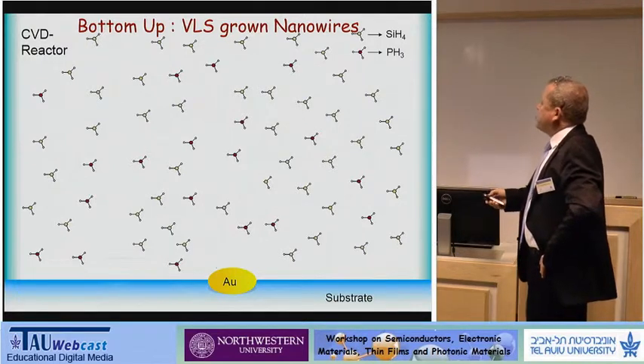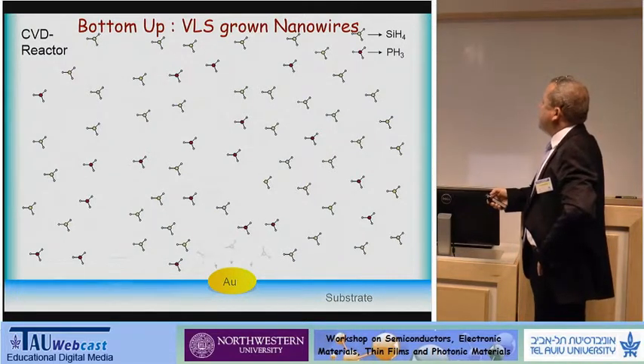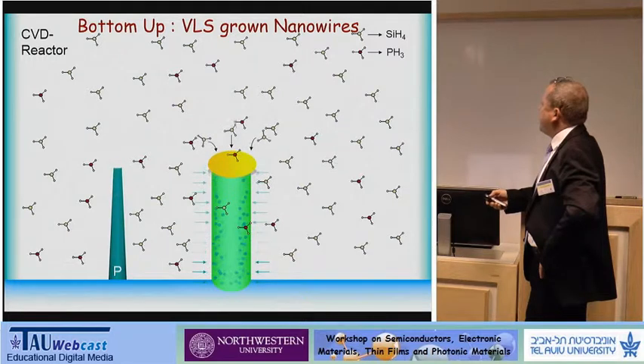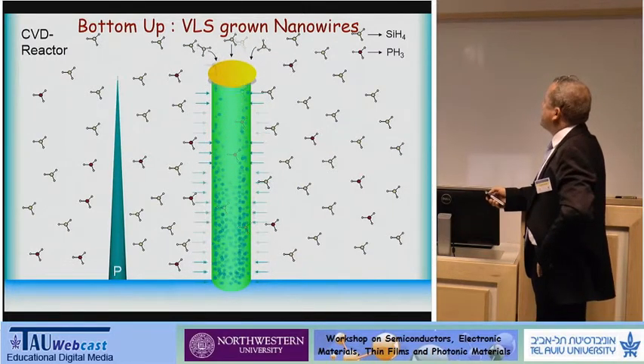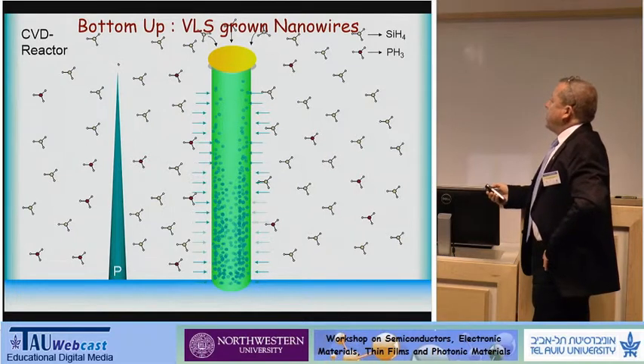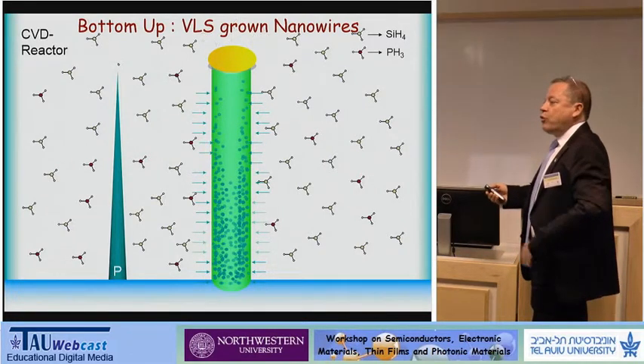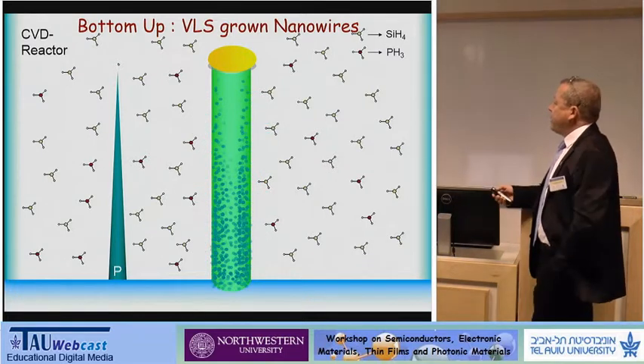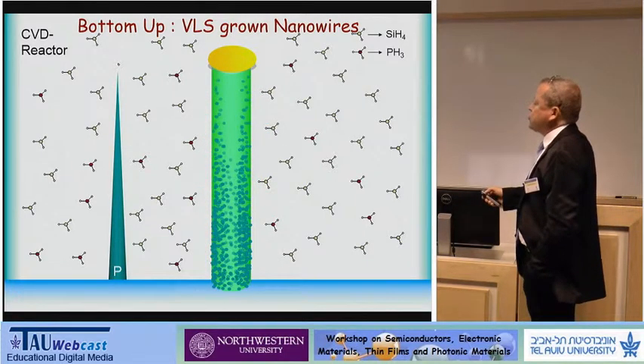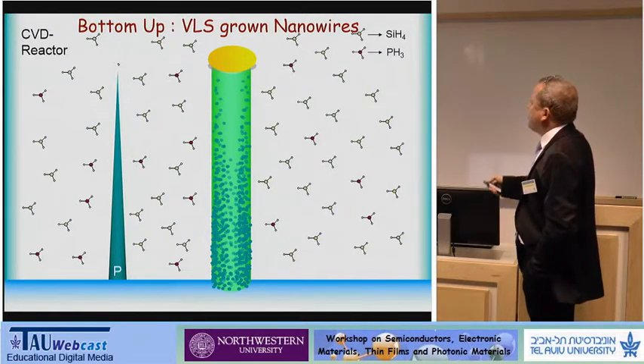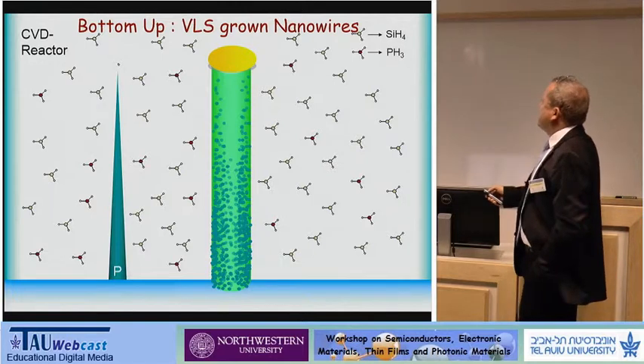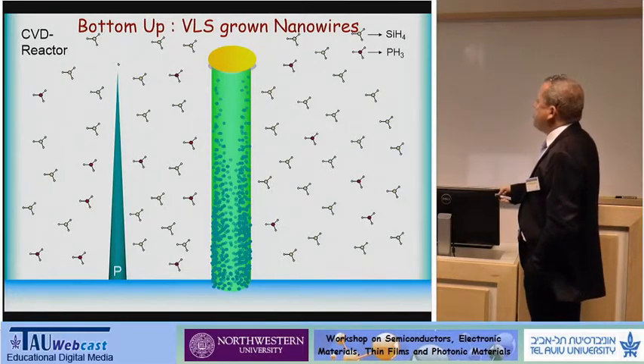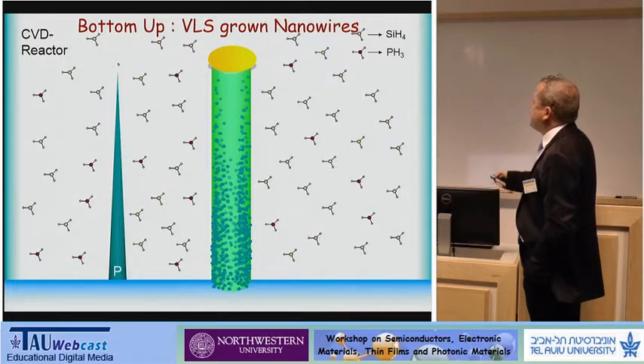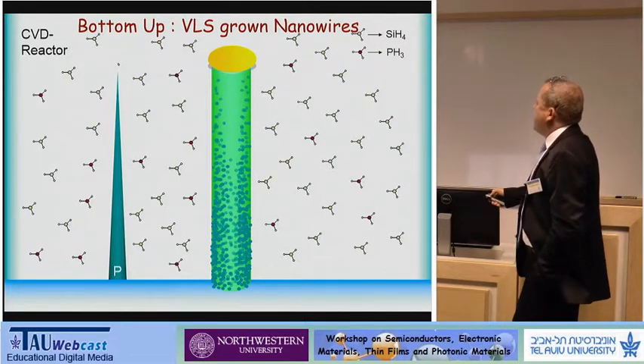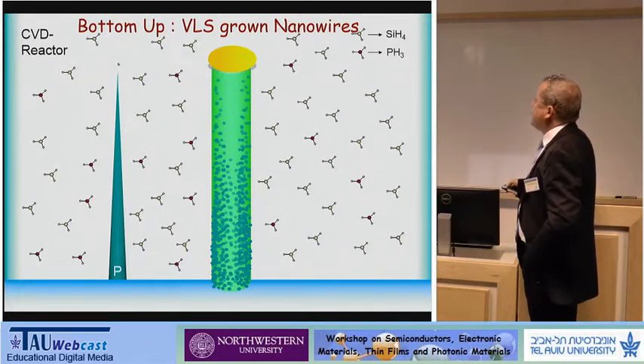The bottom-up technique, the most common bottom-up technique, and this is from Lieber's lab, is the VLS. When you put a gold catalyst and you grow the nanowire vertically like a mushroom inside a CVD reactor. An important issue here is the distribution of dopants. The electrical properties of nanowires are dominated by dopants, and if you want to have a control device or a control p-n junction, you need to control the dopant concentration. And you can see here immediately that in this configuration, you have inhomogeneous dopant concentration along the wire just due to the mushroom growth, and also very inhomogeneous radial distribution.